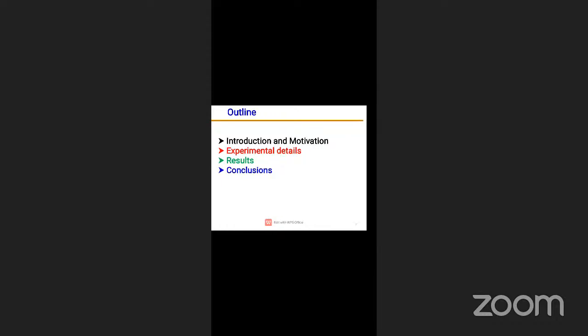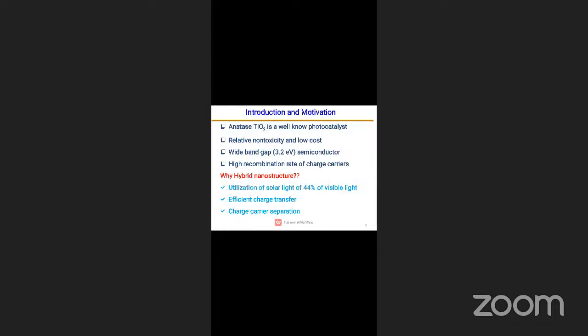So this is the introduction part where anatase is a well-known photocatalyst, a very active material for environmental pollution degradation of dyes. Anatase is better as compared to the different forms of TiO2, such as rutile and brookite. Its advantage compared to the others is relative non-toxicity and low cost. TiO2 and zinc oxide are wide band gap materials, with band gap in the 3 to 3.5 electron volt range. The anatase bulk band gap is 3.2 electron volt.